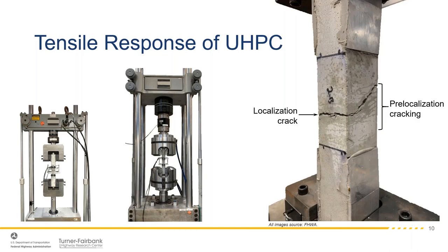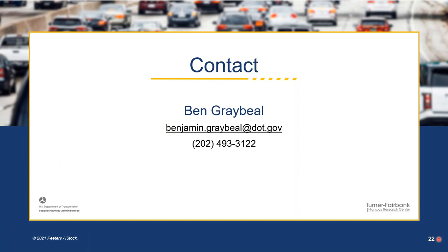Okay. Now the next question came in during your talk. Do the shear connectors from the pre-stressed concrete beam to the deck require any special design considerations given the two f'c values on the deck and the beams? To put it in a nutshell, what we recommend is that you look at the weaker of the two materials. If you're connecting a UHPC component to a conventional concrete component, then your resistance is going to be driven by whichever one's weaker, which generally is going to be the conventional concrete side. The only little caveat is at the actual interface, when you have to decide what your c value and your mu value are for interface shear friction, the friction between the two surfaces. The UHPC side might actually be slipperier, so it might be the one that offers lesser resistance in terms of that cohesion or friction coefficient.